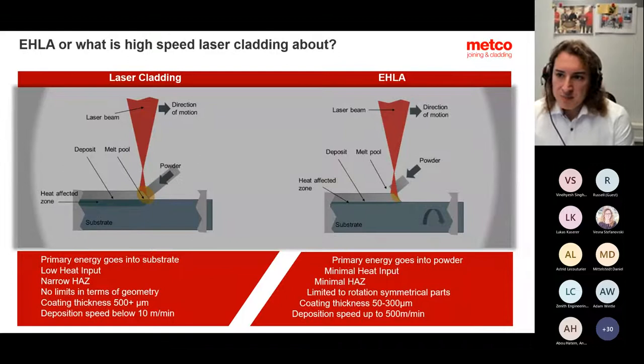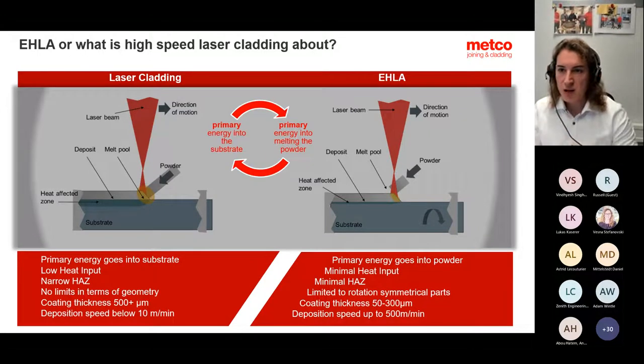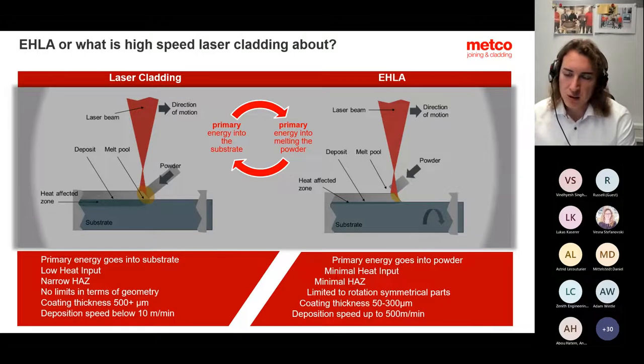What is the so-called high-speed laser cladding or extreme high-speed laser cladding? The fact is very simple. In conventional laser processes or laser metal deposition, you try to interact between the laser beam and your filler material on the surface, where you also produce your primary melting bath on the surface. In high-speed processes, you basically put your primary energy into melting the powder before it interacts with the surface. So it helps you to minimize even further the energy input to the surface by preheating your powder particles before they interact with the surface. And that helps you to get a lot of velocity to your components.